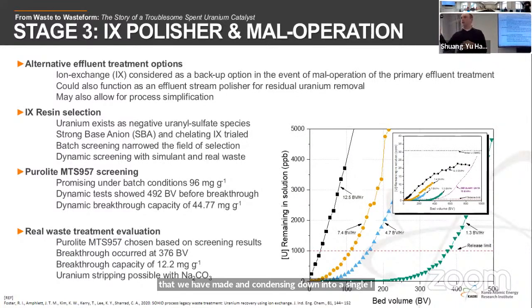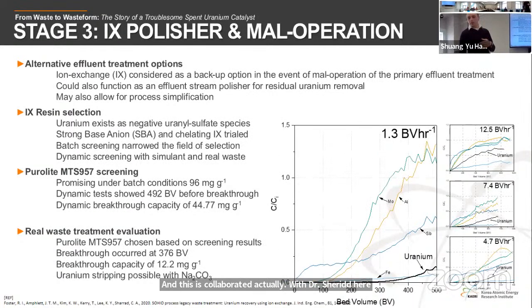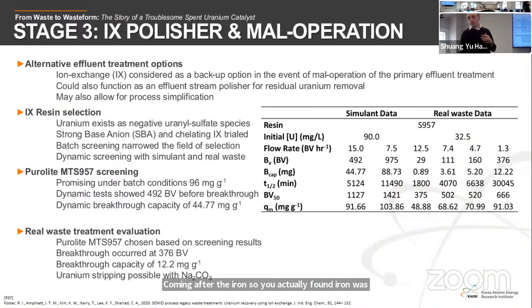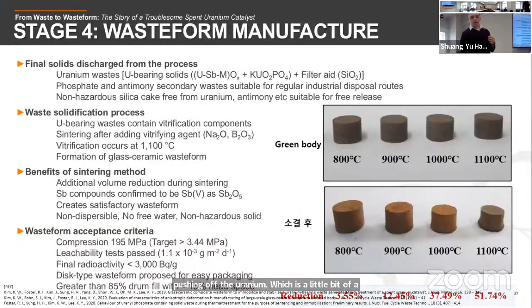And this was collaborated actually with Dr. Sherrard here at Manchester. It proved quite successful in lab testing. However, when we actually then moved to the real waste, we did have a problem where you actually got breakthrough coming after the iron. So you actually found iron was pushing off the uranium, which is a little bit of a problem. So essentially, we were able to use this process as a polisher rather than a main separation process, but it was a good collaboration nonetheless.